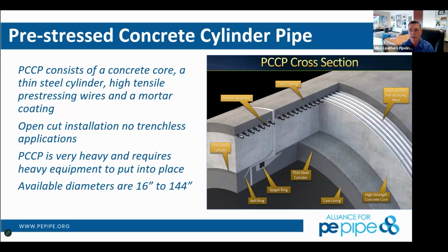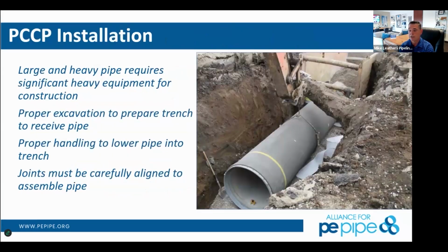Then this steel and this wire has to be protected from corrosion, and that's accomplished with embedding it or lining it, and then on the wire, basically coating it. So all this was providing diameters that can exceed what we were seeing at the time in cast iron and some others. It also helped create some deeper installation requirements for some live loads. And this was accomplished mainly because of the rigidity of the pipe, but also the bedding and backfill, which are important. So PCCP is a great product when it's designed and manufactured correctly, but a lot's been learned over time around wire and some of the issues specifically of one manufacturer, mortar, concrete, steel, and the interactions with soil and other corrosion mechanisms. Much of these learnings are being addressed by manufacturers and specs.